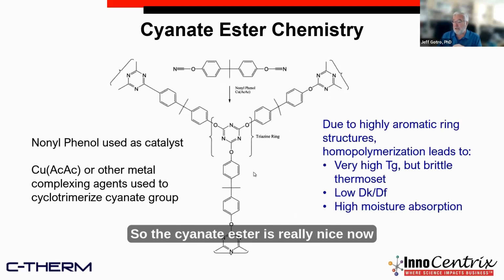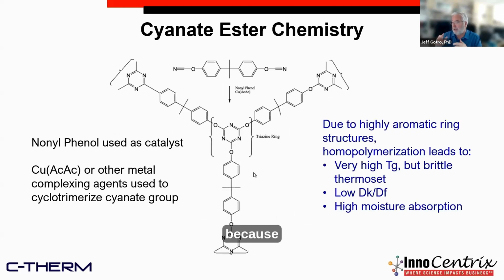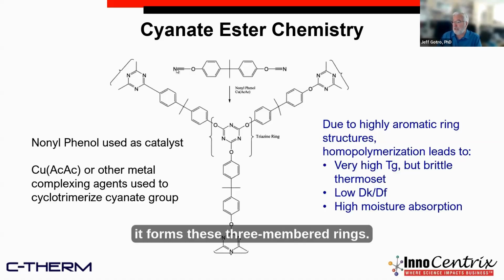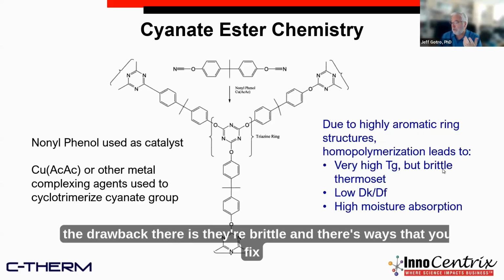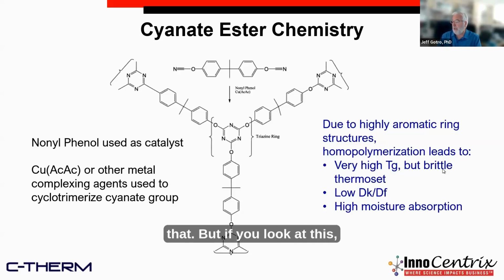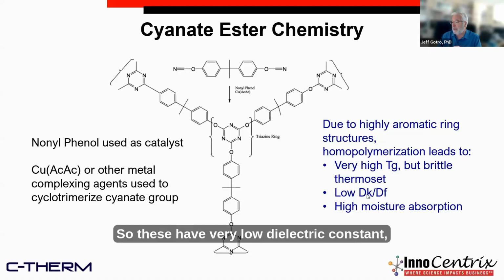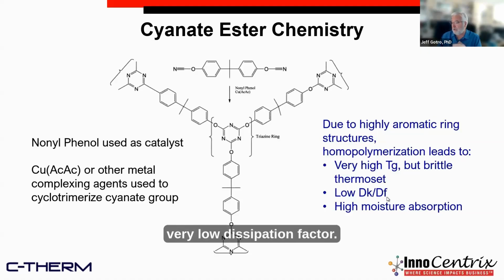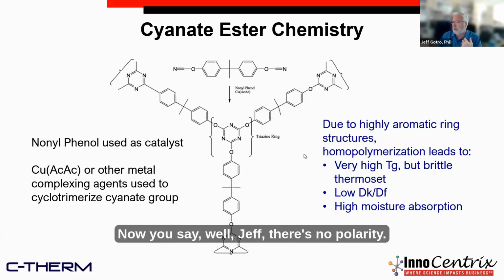So the cyanate ester is really nice now because it forms these three-membered rings, so we get a really high TG. But the drawback there is they're brittle, and there's ways that you can fix that. But if you look at this, there's very little OH groups on here. In fact, there's none. There's very low polarity. So these have very low dielectric constant, very low dissipation factor. Now you say, well, Jeff, there's no polarity. How do they have high moisture absorption?